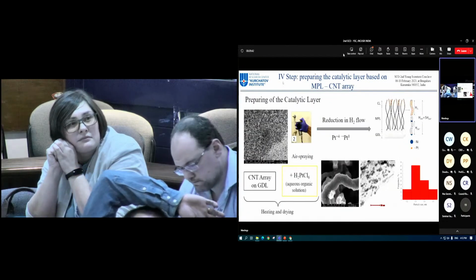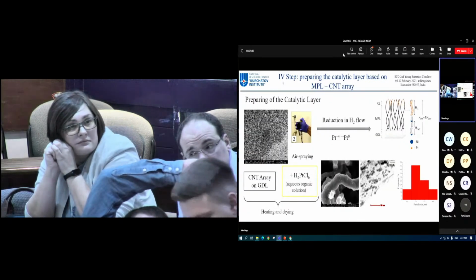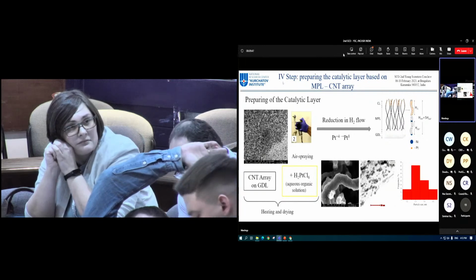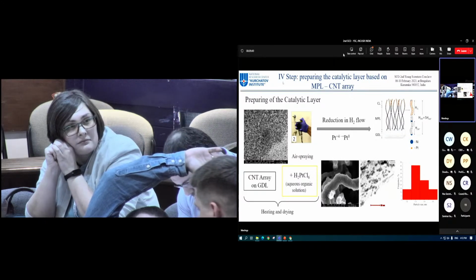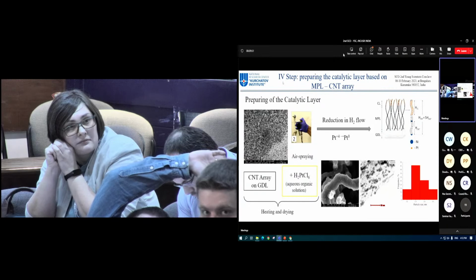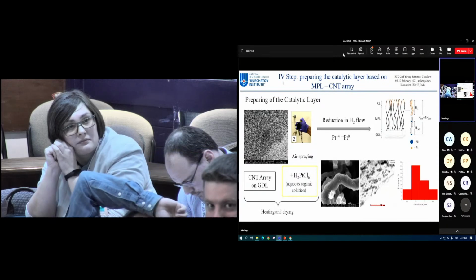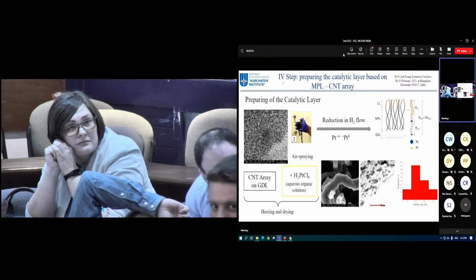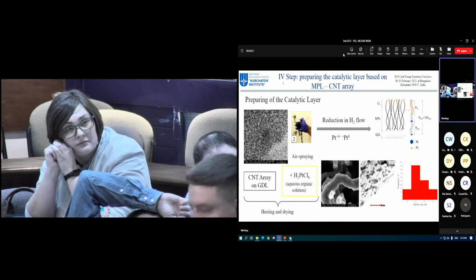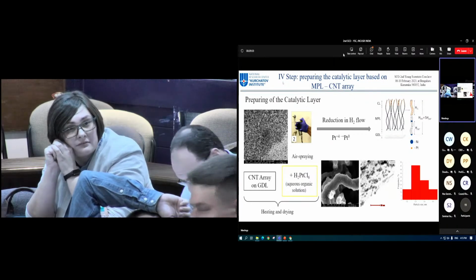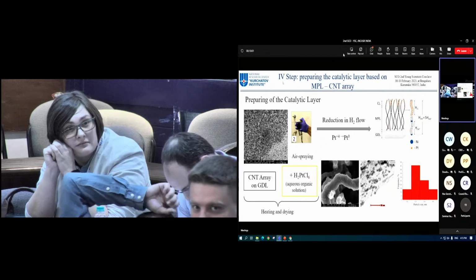The step is preparing the catalytic layer based on CNT array. The microporous layer was first impregnated with the platinum precursor salt by soaking in an aqueous solution of the salt. Then the salt was reduced to platinum metallic nanoparticles in a neutral medium using hydrogen gas. The resultant structure is shown on the slide.